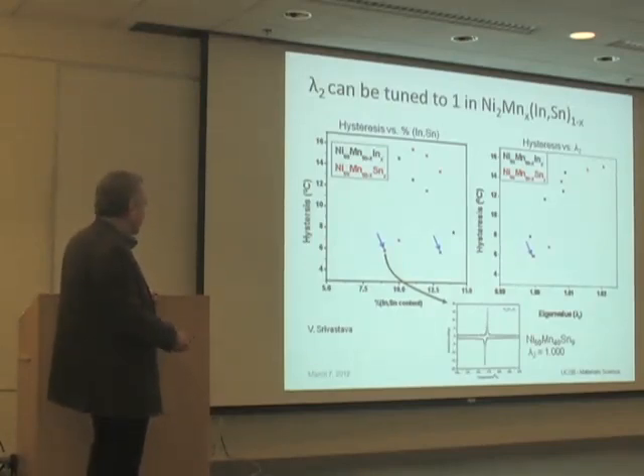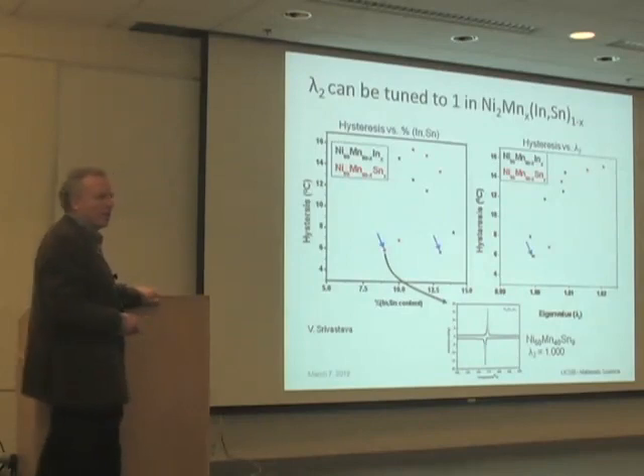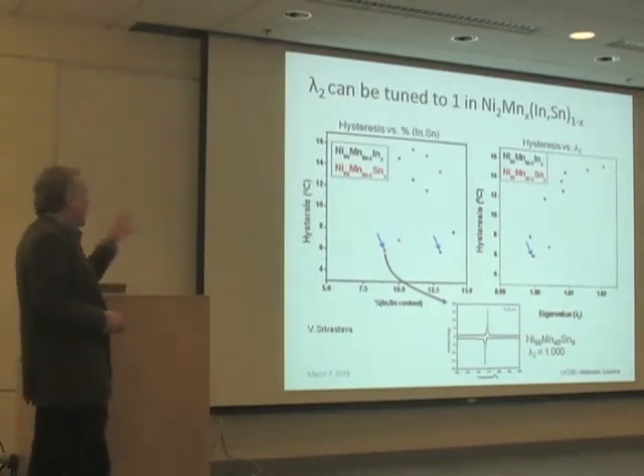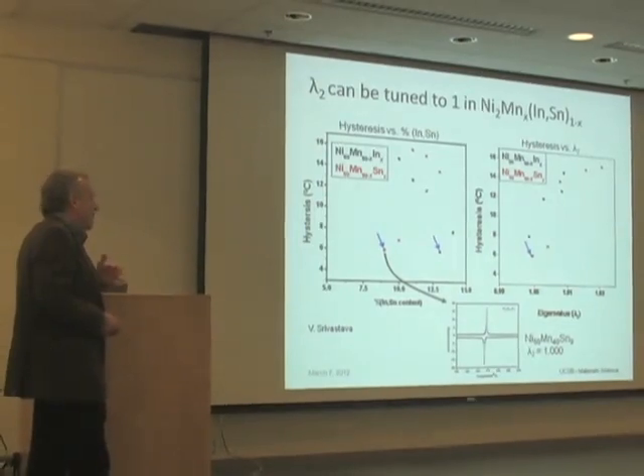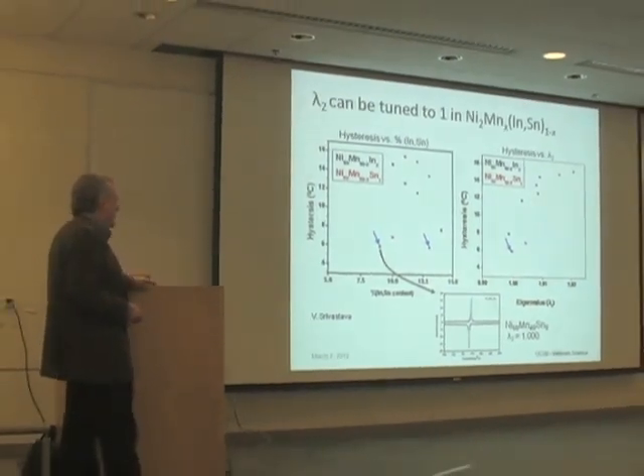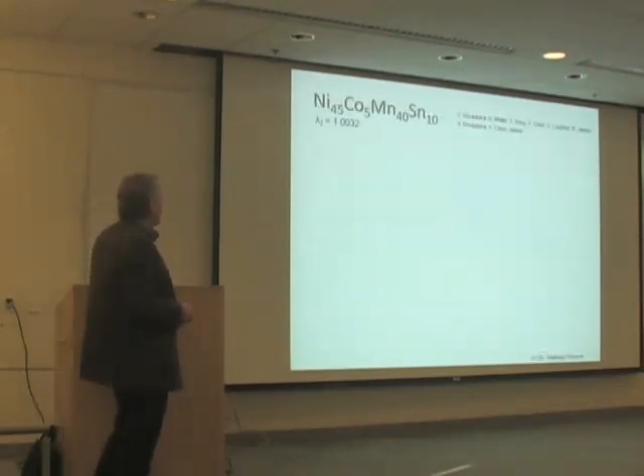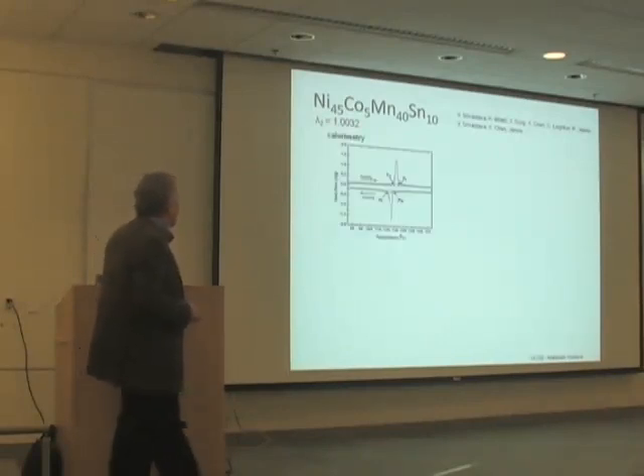It didn't have any strong magnetism, but we had an idea based on some heuristics, let's say, how to get strong magnetism in this alloy, and this is by substituting cobalt for nickel. So this is the alloy we ended up with. It has lambda 2 quite close to 1. It again has about 6 degrees hysteresis. There's a DSC graph. Transformation temperature is near 130, 140 C.